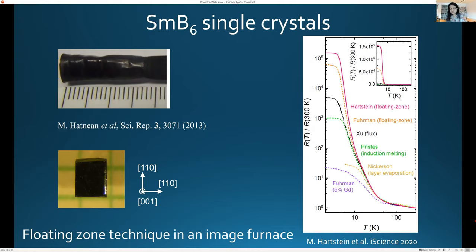So instead, we choose to use floating zone crystals that are grown solely from samarium and boron at very high temperatures. This is congruently melting material. So this can be grown largely without too much additional cell flux of either samarium or boron. We then, so this is a big boule of this material. So it's several inches in length. We then cut pieces from the single crystal and then do very, very extensive screening procedures.